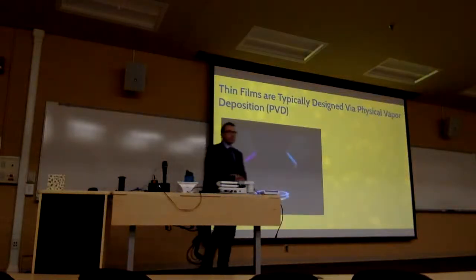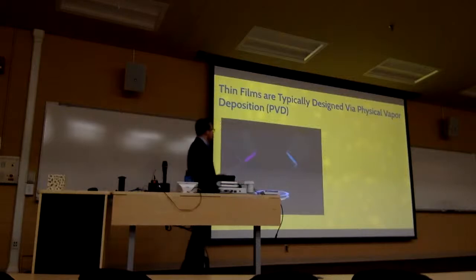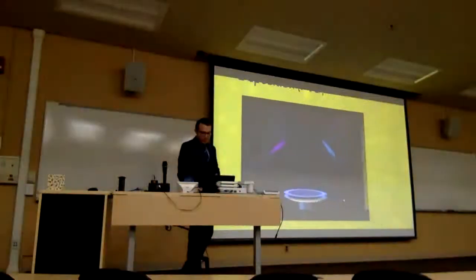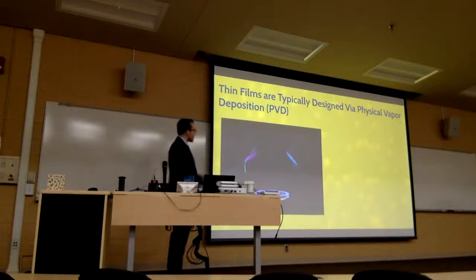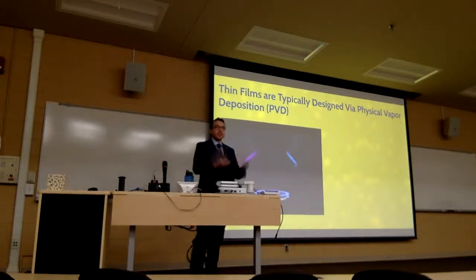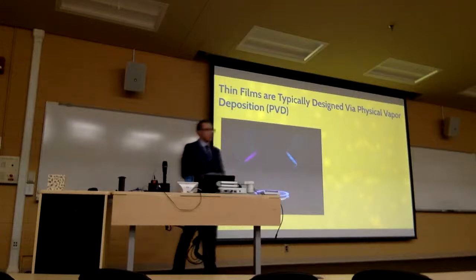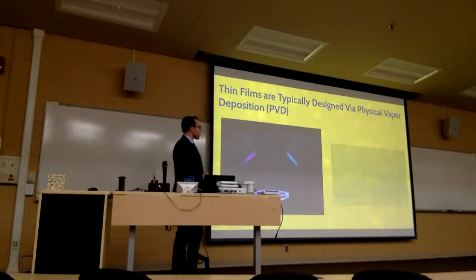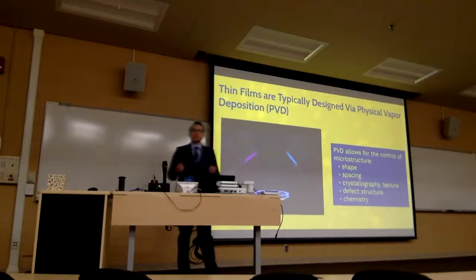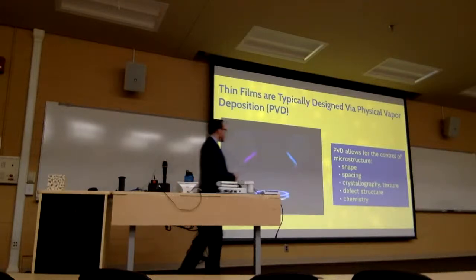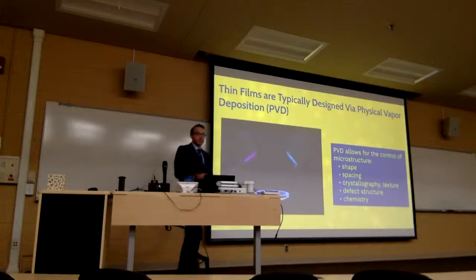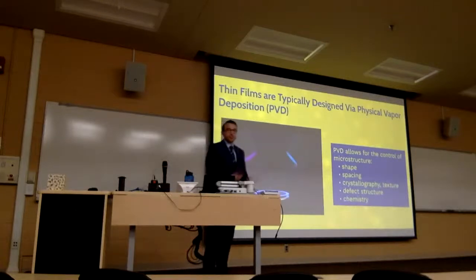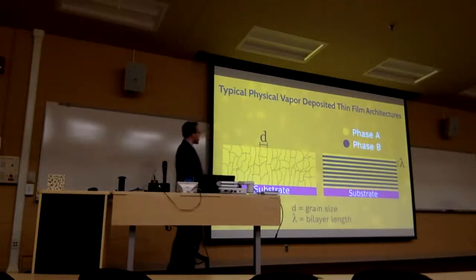How thin films are typically engineered or designed is through a process known as physical vapor deposition. But what the name implies, this, my video is not going to load here. What the name implies is that we're actually vaporizing a material in a chamber, and it condenses onto a substrate, another material, in very thin layers, in atomic layers, to grow a thin film material. Why we use this process is that PVD allows us to control certain aspects of the microstructure, namely the shape, the spacing, the crystallography, and the chemistry of the thin film, which again plays into the properties in those applications I described before.